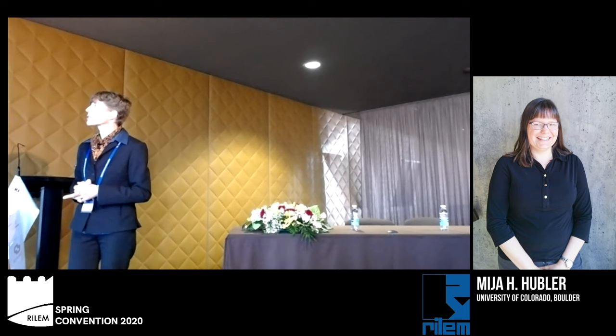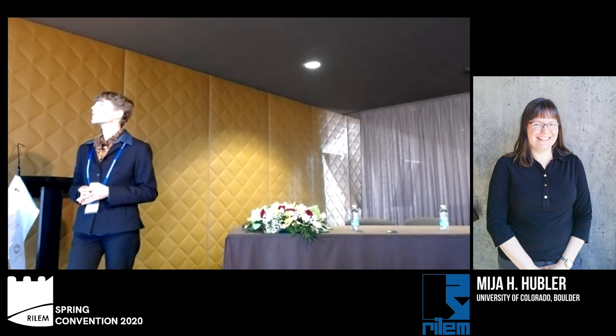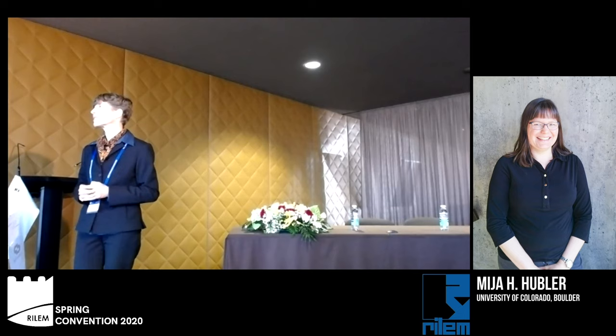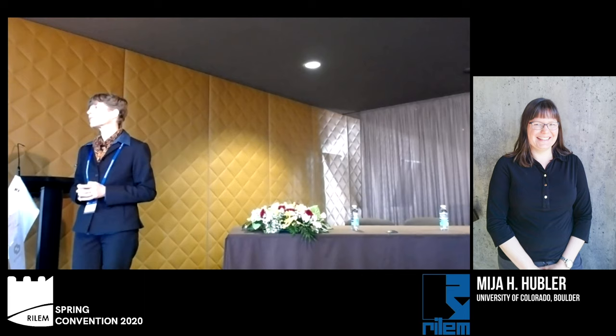The effect of temperature does appear in a number of existing prediction models. Generally, temperature accelerates the aging processes within the cement, and so as a result, what we see is a time acceleration of the creep or the shrinkage behaviors, or you could say a later time behavior.